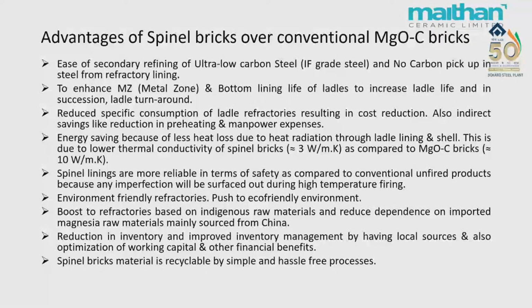Then we will reach the reduced specific consumption of ladle refractories, resulting in cost reduction and heating and manpower savings, etc. So the most important factor in spinel bricks nowadays, we are talking about energy conservation. So energy saving is the major issue. As spinel refractories are less thermally conductive, 3 versus 10 watt per meter per Kelvin, that gives less heat loss in spinel refractories.